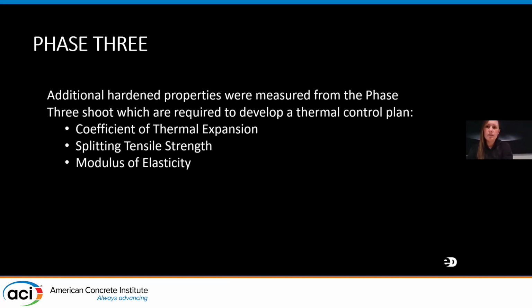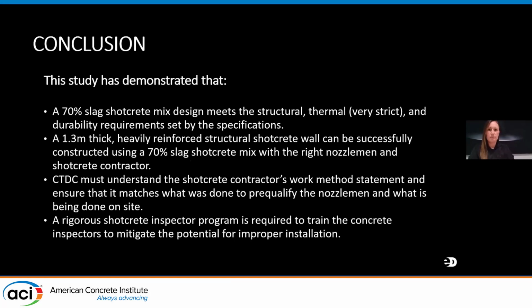Additional hardened properties were measured from the phase 3 shoot, which are required to develop a thermal control plan for the mass shotcrete as well. So we did coefficient of thermal expansion, splitting tensile strength, modulus of elasticity, and I believe I left Ellis at that point, but the team continued to go through this process and create a thermal control plan for them. And now I know that the project is implementing the use of mass shotcrete in 3 of the stations, and I'm sure it'll be expanding into more of them.